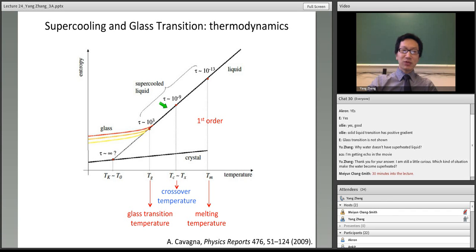But if you just look at the entropy or enthalpy or the specific volume of the system, there's no clear transition. This is not a transition either, but from the dynamics, you can see there's a clear change here. So the crossover temperature is oftentimes underestimated. A lot of people talk about the glass transition temperature, but nowadays the opinion is that the crossover temperature is probably as important as the glass transition temperature, in the sense that the crossover temperature is more well defined, and a lot of phenomena happen at the crossover temperature.